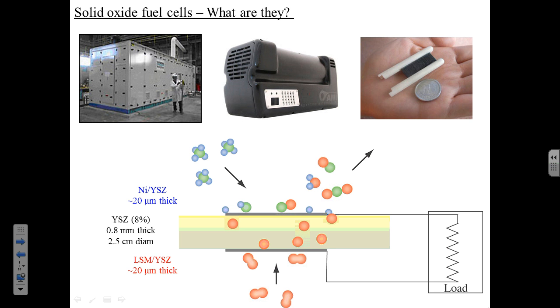In a solid oxide fuel cell, the start of the food chain starts at the cathode, where molecular oxygen comes up to the cathode. It's reduced to make oxide anions. Those oxide anions diffuse through the solid oxide electrolyte to the anode, where they react with fuel, shown here schematically as methane coming in. The oxides react with the fuel to produce carbon dioxide, water, maybe carbon monoxide. And what comes out is electricity.